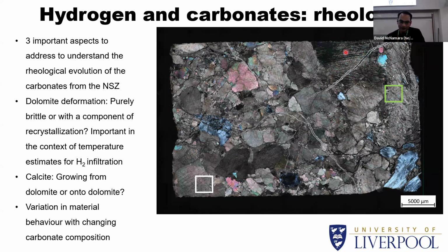And then you've got these fringes here, where you've got calcite in between dolomite. Now, it could be that the calcite is growing from dolomite, it's growing onto dolomite, or it's just a calcium-rich fluid that infiltrated the fractures, and all of this story does not make any sense. And then dolomite and calcite behave very differently in terms of their response to stress. So deforming a dolomite-rich rock and deforming a calcite-rich rock would require very different PT conditions and stress conditions. So if we change from dolomite to calcite within a rock, we would expect a variation in the material behavior, so that also needs to be quantified.